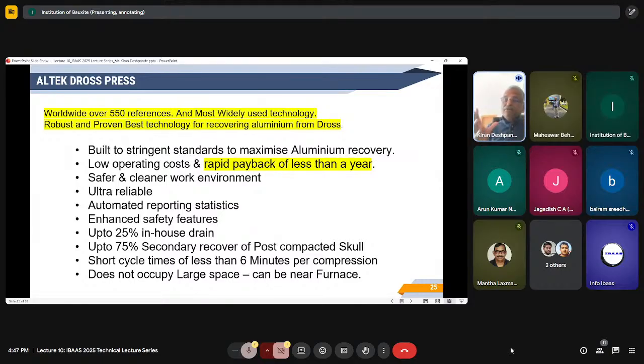Now we are coming up with a technology where we can actually see the weight of the DROSS when it goes inside the press and then when it comes out of the press. So it gives you 25% in-house drains. So 75% aluminum is trapped in the skull, and it is not aluminum oxide due to thermiting. When there is pressing, the press head and the pan both become a heat sink. So it immediately absorbs the heat out and the DROSS cools and the aluminum gets solidified inside the skull, which is 75%, which you have to recover, for which ALTEK has AluSalt or REM technology.